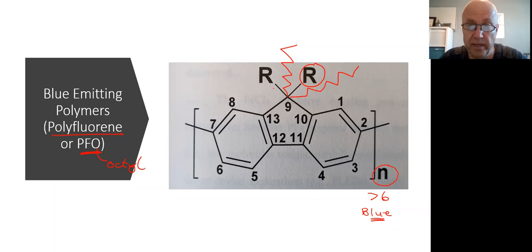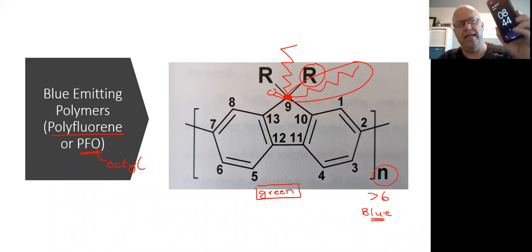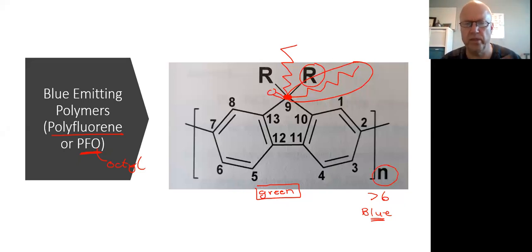Now, the key problem with these materials is this point right here. These are not very stable units. And it doesn't take much for this to break off and you end up getting a ketone here. And if you get a ketone there, this thing will now emit green. So that was the main problem with these materials, that this would eventually emit green. Because these devices inside here can get up to 80 degrees Celsius, you have oxygen diffusing in, and over time, your material degrades. And so my PhD was focusing on making new materials that would prevent the formation of this ketone here.